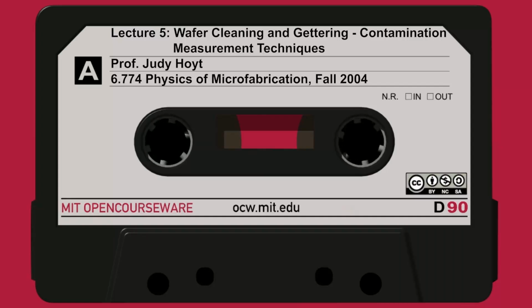This brown curve up here that's marked EOT, the equivalent oxide thickness, is referenced to the right-hand vertical axis, which shows the equivalent oxide thickness in angstroms. So this is exactly the data I showed you going down. Starting in 2003, we have an EOT of 13 angstroms on the right, and it's going down and down, so that by 2007 or so, the EOT is nominally 9 angstroms. So this is the way people would like to scale, but clearly in the next few years, oxynitride is not going to work. You're going to need some other material, like hafnium oxide or one of the silicates that people are studying.